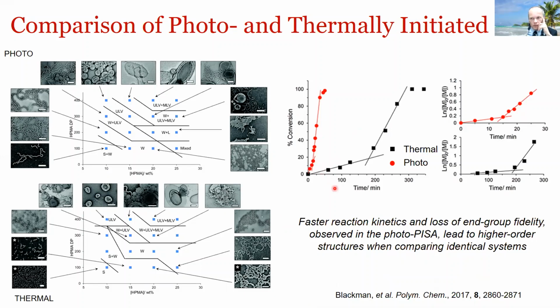the photo initiated PISA is significantly faster, and a characteristic feature of PISA polymerizations is that you see this acceleration in rate of polymerization upon assembly. So as I said, as the construct forms, you then get this step change and increase in polymerization rate. And you'll see, for the same polymerization initiated in two different ways, either thermally or photo, the point at which this assembly occurs is around 15 minutes for the photo and about 200 minutes for the thermal.